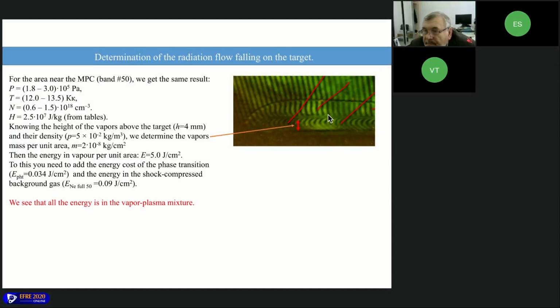And for band number 50, we get some result, and the code calculates the enthalpy for these parameters. Knowing the height of vapors above the targets is about 4 millimeters, and the density, we determine the vapors mass per unit area. The energy in vapor per unit area is about 5 joule per square centimeter, and if we sum it with the phase transition and the energy in the shock compressed background gas, we obtain near 5 joule per square centimeter.